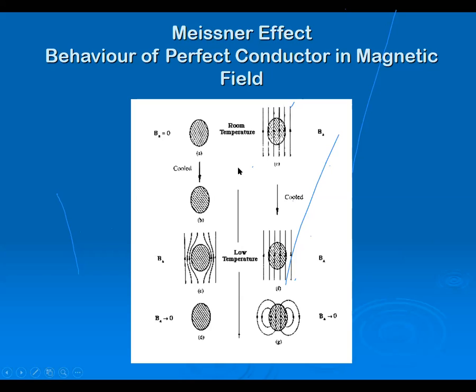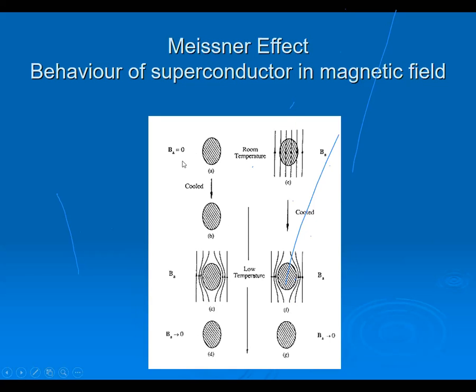The point is that it is history dependent here, whether you cool it in zero field or you apply the field and cool it. And then when you switch off the field, you will see that it depends on the history. If it was in zero field, there is no flux trapped, whereas if it had the field, there are flux lines trapped. This is what would happen in a perfect conductor. But when we have a superconductor, what happens? Irrespective of whether it was cooled in zero field or applied field, once it is cooled below the transition temperature, it always shows expulsion of flux. This is your Meissner effect.